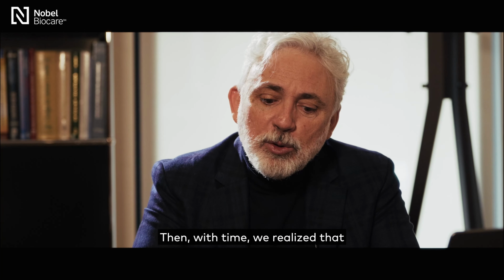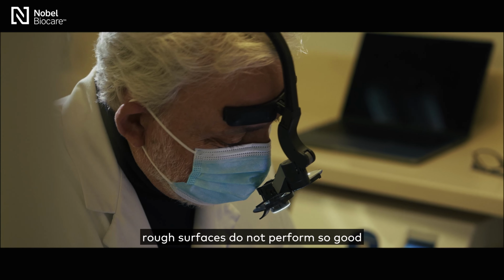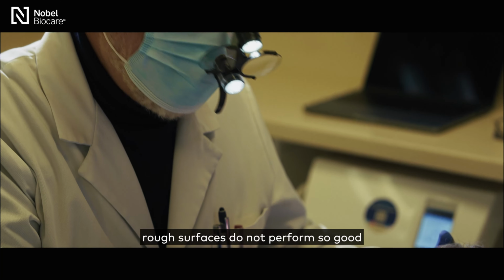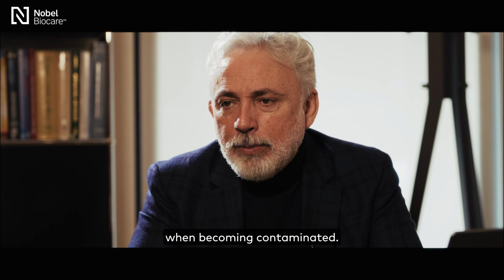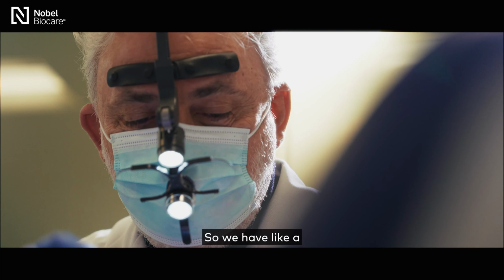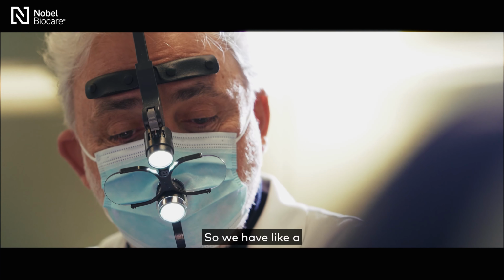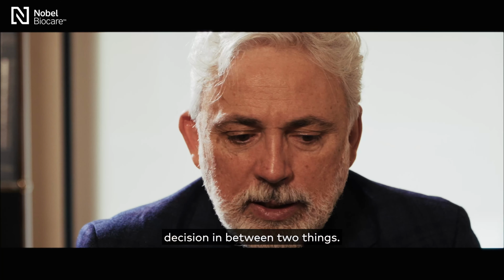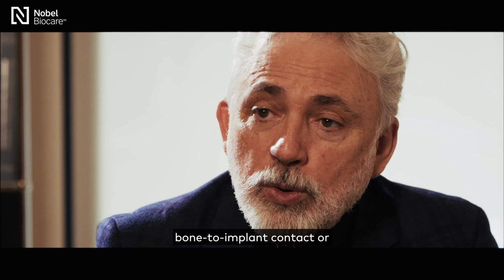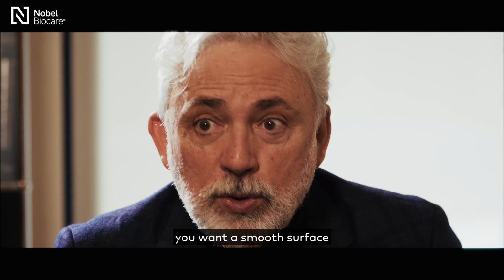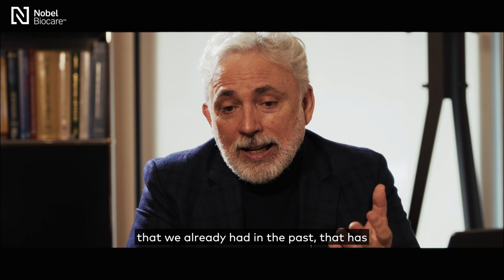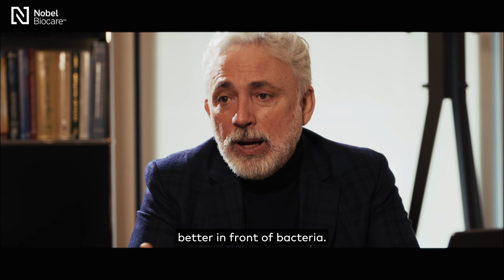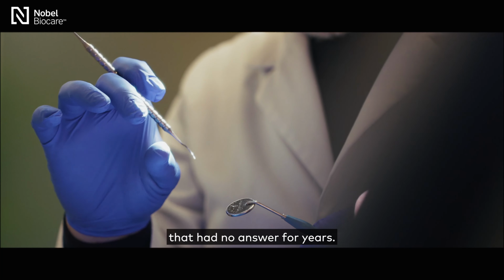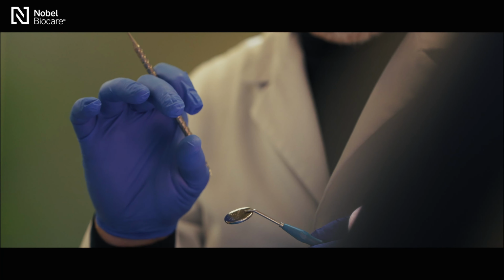Then, with time, we realized that rough surfaces do not perform so well when becoming contaminated, okay? So we have a decision between two things. What do you want? You want a lot of bone-to-implant contact, or you want a smooth surface like we already had in the past that has less bone-to-implant contact but performs better in front of bacteria. And that was a dilemma that had no answer for years.